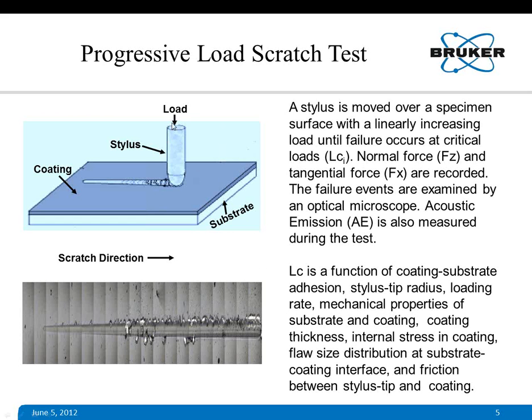The progressive load scratch test is shown on this view graph. You can see that there is a stylus which is used for this scratch test. It starts at some point on the coating, and it is dragged over the surface of the coating with linearly increasing load. The normal force, which is the load, and the tangential force, that is the friction force or Fx, are measured. After the test is done, an optical microscope is used to get an image of the scratch. From the image, we can see where the coating is failing.